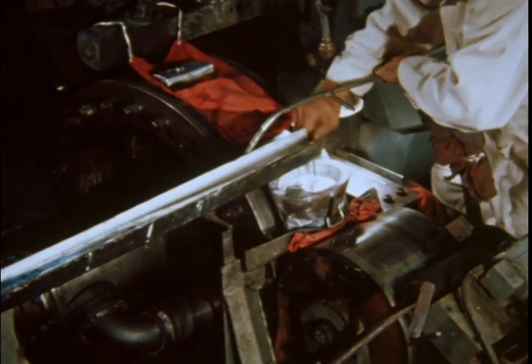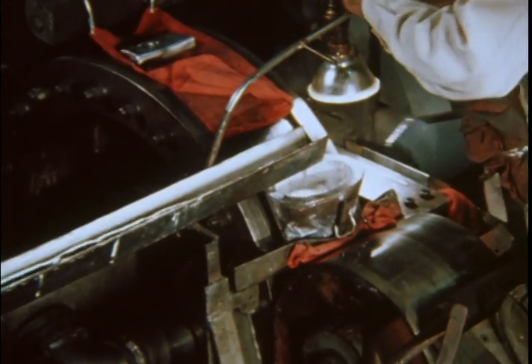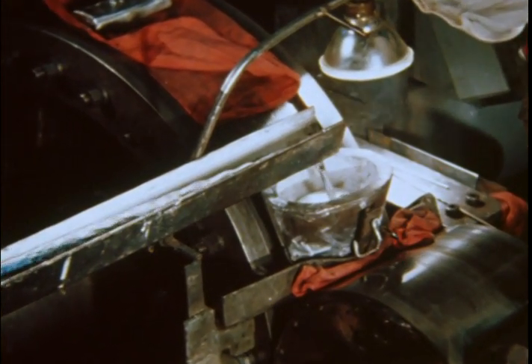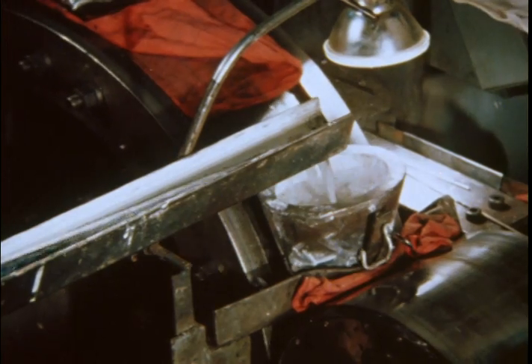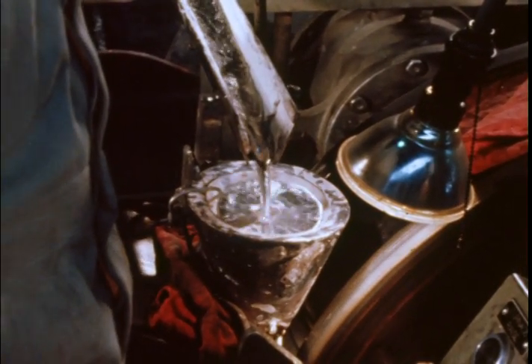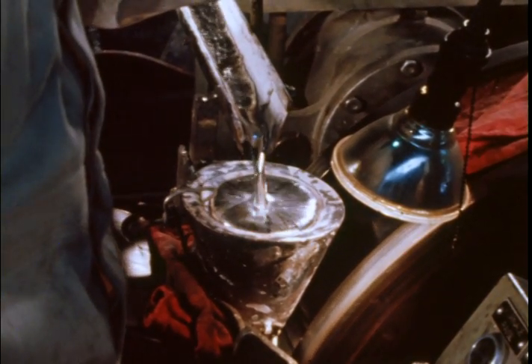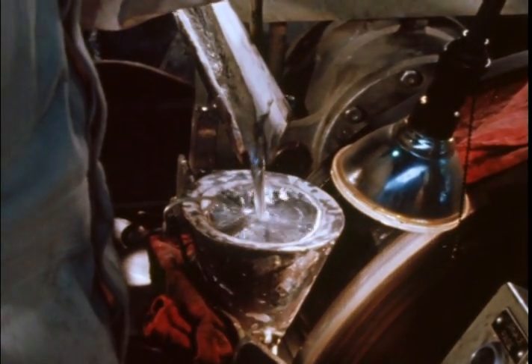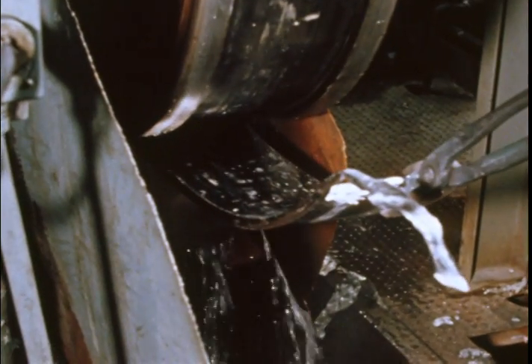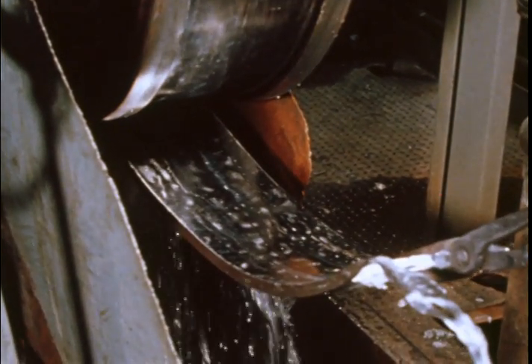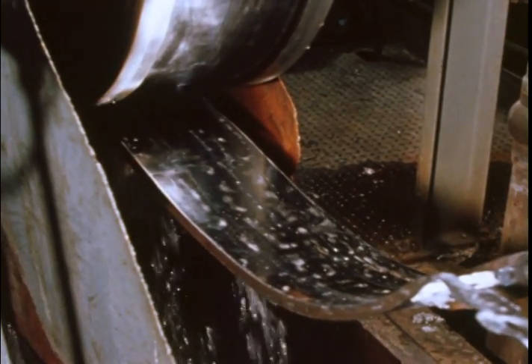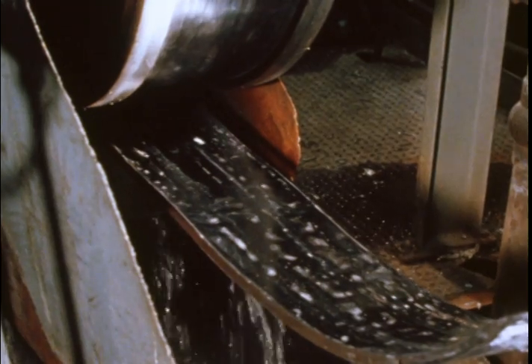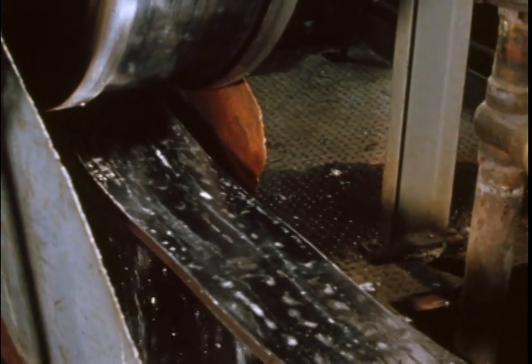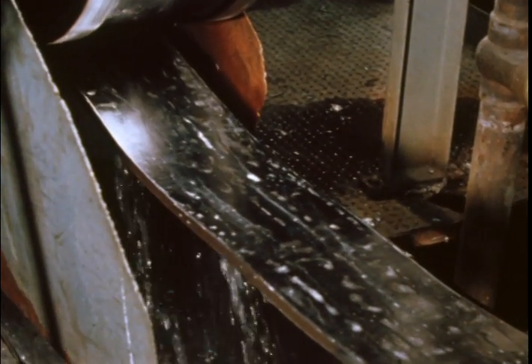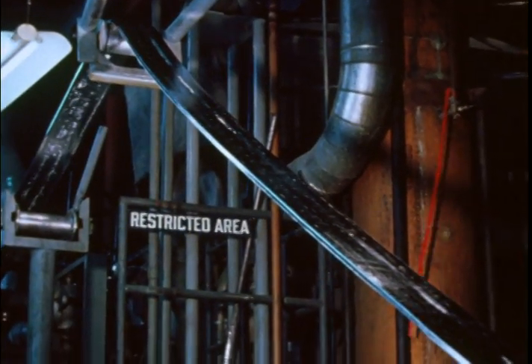Molten aluminum pours from the discharge of the furnace into the casting machine. The molten aluminum is solidified between the surface of the wheel and a metal band and emerges from the underside of the wheel as a continuous aluminum strip. We are casting here at the rate of approximately 3,000 pounds of aluminum per hour.